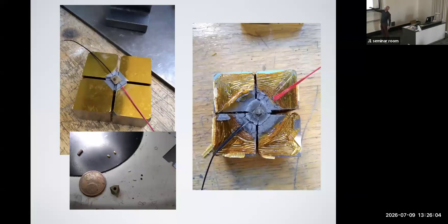So the temperature on the inside here is up to 2,200 kelvins without flowing, right? Without deforming over the course of the experiment, which of course would change the pressure, right? So there's lots of actual material science going into designing and making this. The octahedron is magnesium oxide. The furnace itself here, I'll show the furnace for scale, right? That's a 5-cent euro coin. That's the furnace, right? The center of this goes to 2,200 K. These are interior parts of the furnace assembly, right? And here's the magnesium octahedron, right?